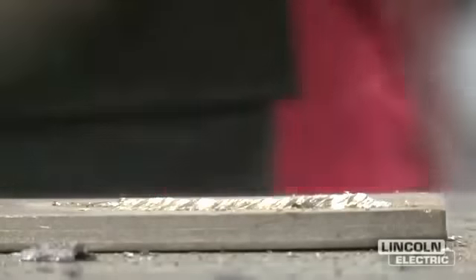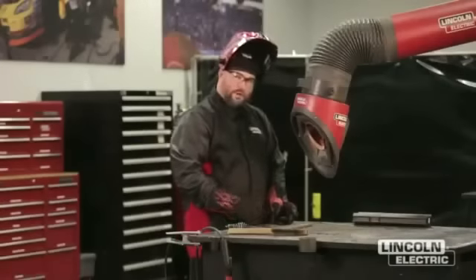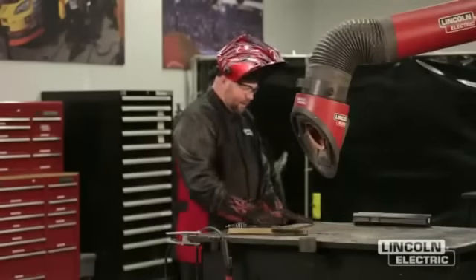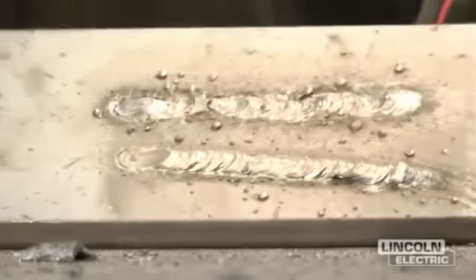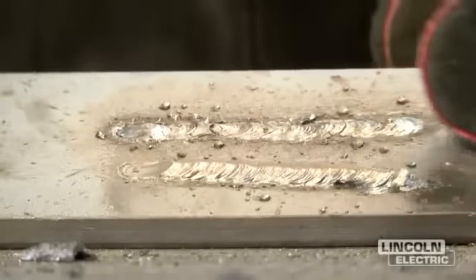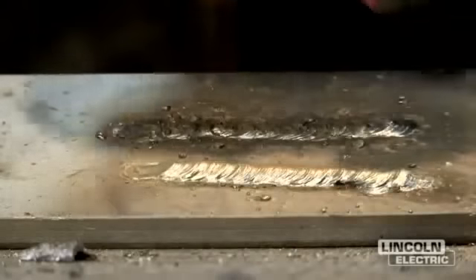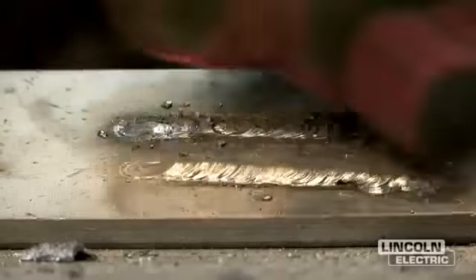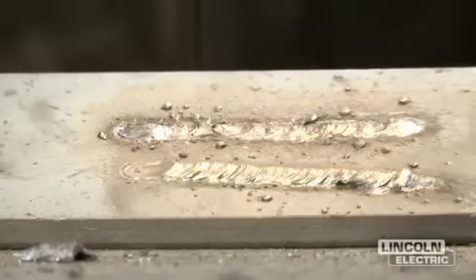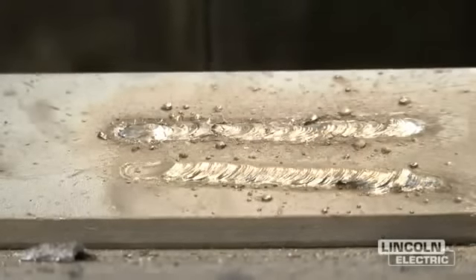Now you'll notice with that long arc length that we held, yeah, it spread out the weld a little bit, but we also got a lot of spatter. And you'll notice too that the weld is real flat, but it's very inconsistent too, in the way that there's not much buildup and very inconsistent in the ripples on the bead.